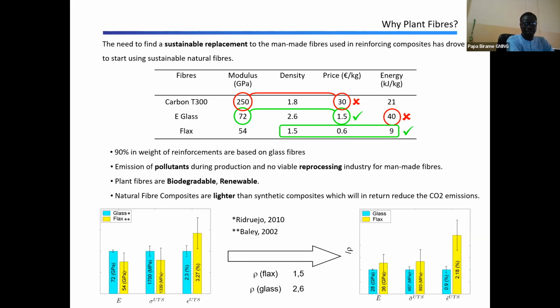Just to illustrate what I'm saying, in the left bar chart you have in blue the modulus, the strength, and the maximum elongation strain of glass fibers, compared to the properties of flax fibers divided by the density, which is 1.5 for flax and 2.6 for glass. We see that the specific modulus and strength of flax start being interesting because they are superior to the specific properties of glass.